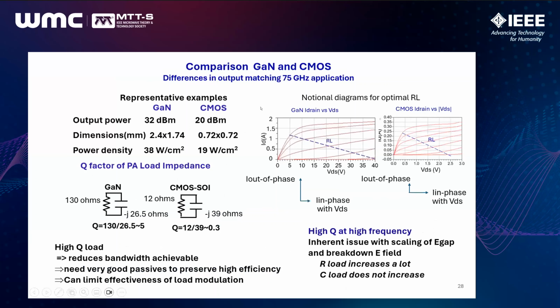As an example of implications, I show here some notional designs for a frequency of, in this case, 75 gigahertz, for a notional gallium nitride device and a corresponding CMOS device. Now, the ratio between voltages applied is immense, and the output power is also really different for the two cases. But if we look at the loads for gallium nitride, the effective load resistance is 130 ohms because of the very large ratio between the voltage and the current. And that's 10 times higher than the value chosen for the CMOS. But the capacitance associated with this is almost on the same order, so that the Q for the gallium nitride device is high, it's 5 at that high frequency. And for the CMOS, it's less than 1. So it's not really an issue.